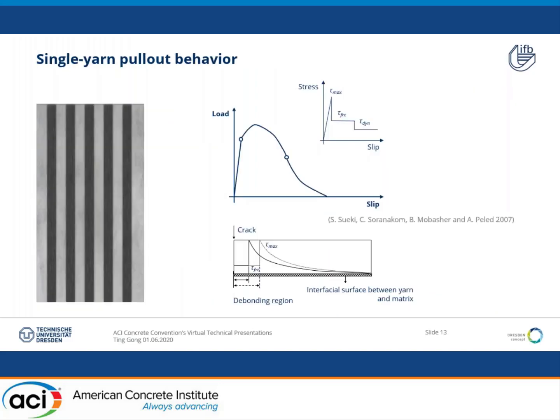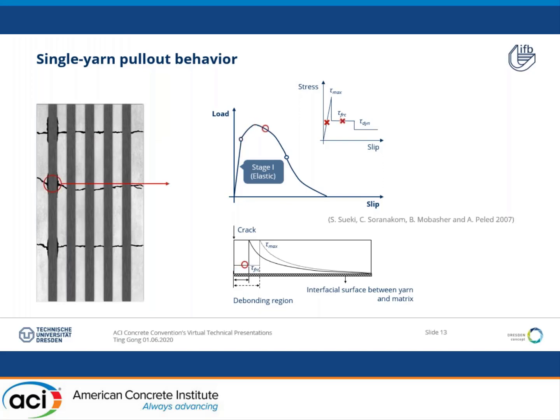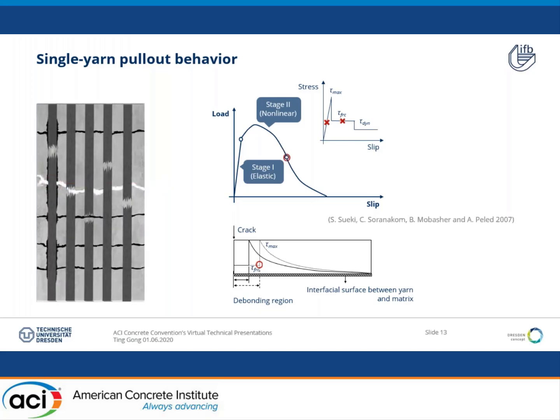The single yarn pullout behavior actually reveals the interaction of yarn and surrounding matrix during the tension test of the composite specimen. For example, as we can see from the figure on the left-hand side, at the beginning of the tension test, both the matrix and embedded yarns are behaving linearly, which corresponds to this linear branch of the single yarn pullout load to slip curve shown on the right-hand side. As the load increases, cracks will happen, and we can imagine that the yarns are being pulled out from the debonding area, which can be referred to the nonlinear stage of the pullout curve. In this stage, the pullout load is contributed by the sum of the non-debonded portion and the frictional force in the debonded portion. After the textile rupture, the yarn will be pulled out from the channel, which corresponds to the third stage, the dynamic pullout stage.